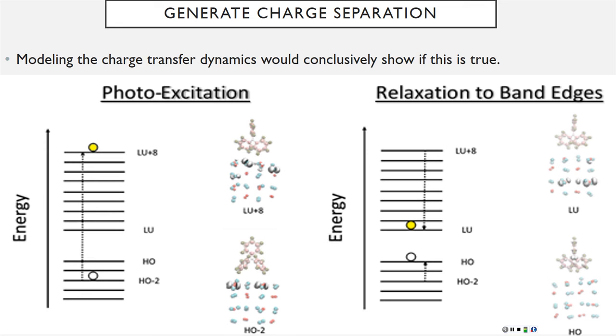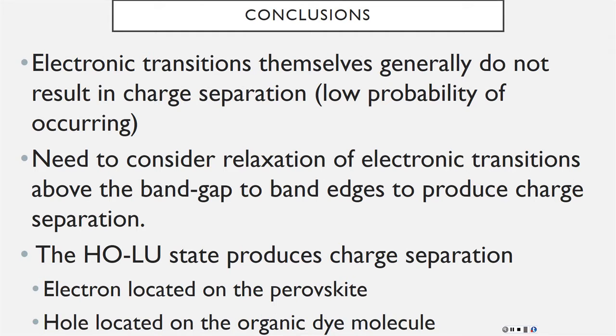To show this conclusively, I would have to do the charge transfer dynamics of this system as the next project to follow up on this. So in conclusion, photo-induced electronic transitions themselves are not enough to generate charge separation. We need to consider the relaxation processes after the photoexcitation to the HOMO and LUMO gaps, where the electron would reside on the perovskite and the hole would be on the organic dye. So the organic dye acts basically as a hole transfer material.